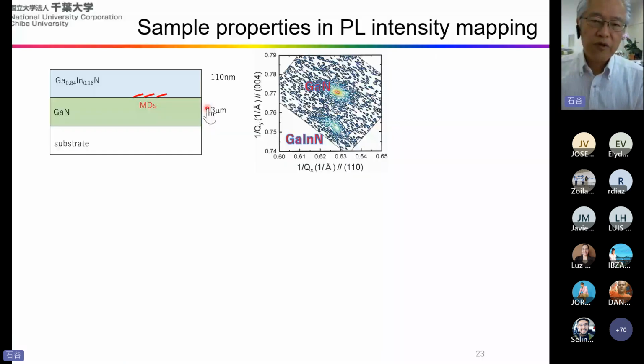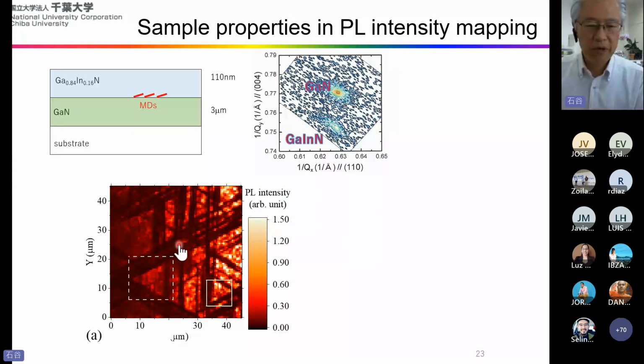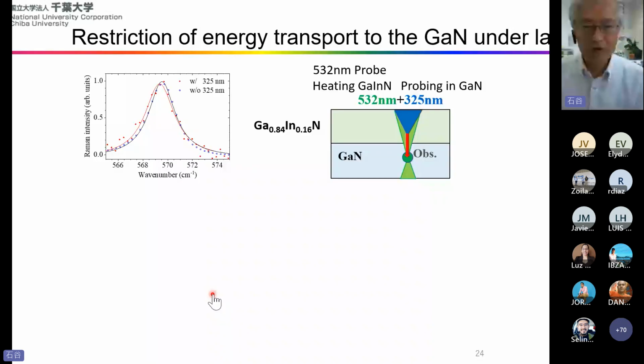So this is an example of the observation. There are some domains with crystal defects and without crystal defects. This is a photoluminescence mapping. The dark line is the place of high density of crystal defects, so the light emission intensity is weak. And this is a low crystal defect region. High luminescence intensity is observed. And we introduced the heating laser and measured by using a green light laser.